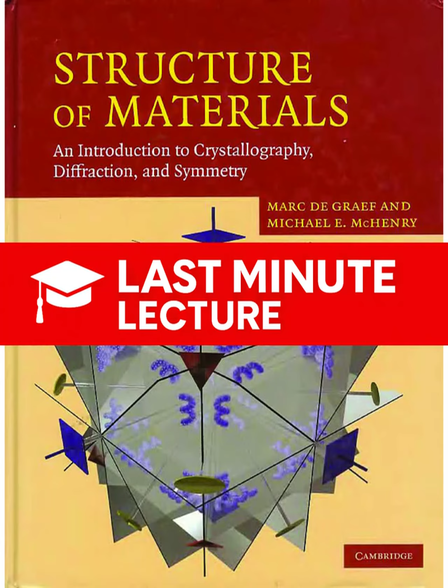Wait, so the basis vectors themselves transform using alpha, but the components of a vector transform using the inverse of alpha? Precisely. If your new basis vectors are twice as large, the components you need to describe the same position vector must be half as large. Hence, the inverse relationship. That is the foundation of tensor calculus and crystallography.